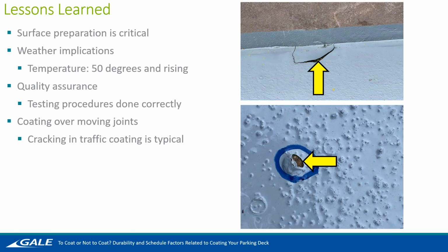So finally, some lessons learned that Kat and I have learned with installing many different types of traffic coating products and different garages and different conditions. A few things: the surface prep is critical. This is really ideal, not just at the beginning when you install your primer, but after each layer. If you're installing the polyurethane system, that takes at least a day to cure. You can imagine at the top level of a parking garage, it's going to see every type of debris throughout a day. It's going to see leaves, dirt. So it's really critical that before the next layer is applied, that surface is cleaned.